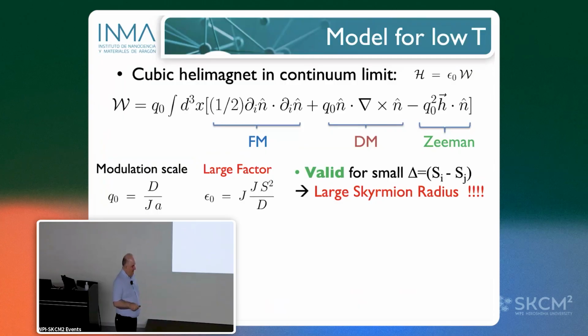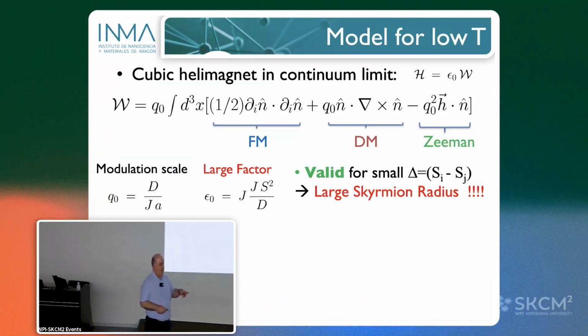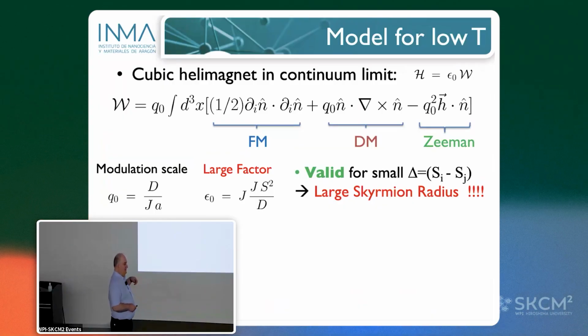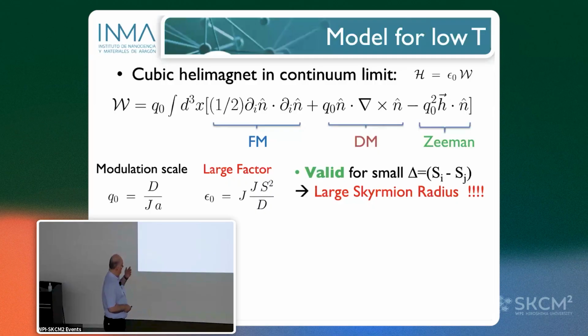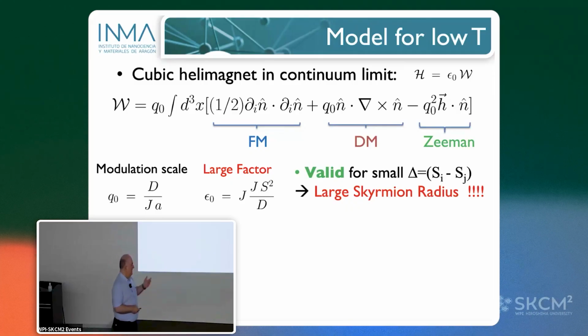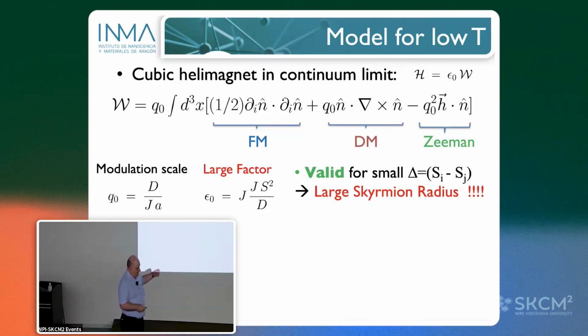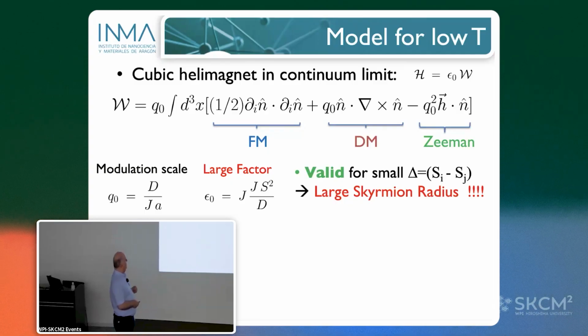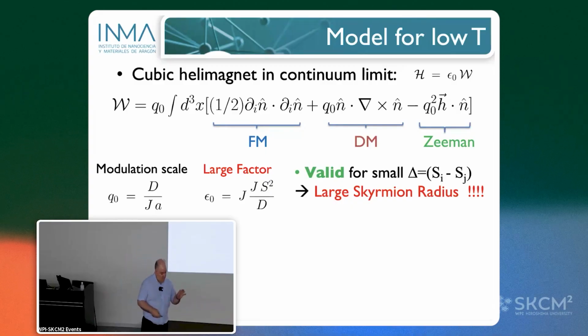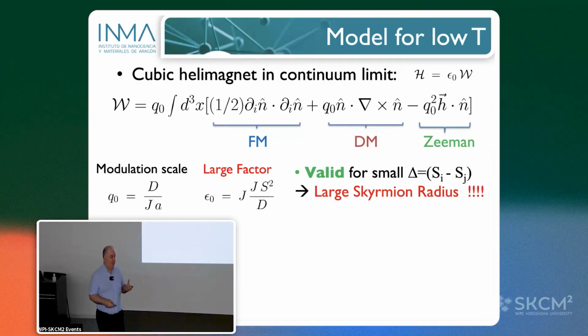this uniaxial model, to solve the problem in the uniaxial helimagnet, people are going to the continuum. That means they are assuming that the variation from one spin to the next one is small. Then, this is true if the skyrmion radius, or the wavelength of the object, is large. That means considering the uniaxial model in the continuum, and going to describe it in the cubic system, because now we are thinking to do some theory to describe what is happening in manganese silicide. But manganese silicide is a cubic helimagnet. Then we need to generalize this in the continuum limit, and considering propagation of the interactions along the three directions.